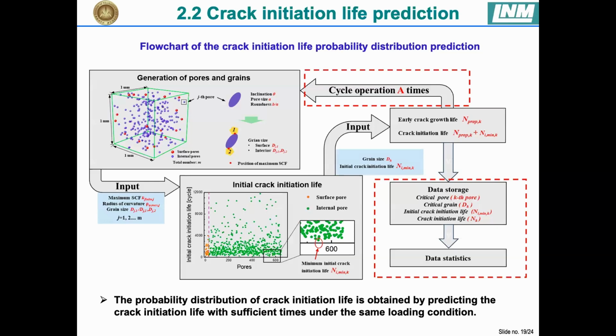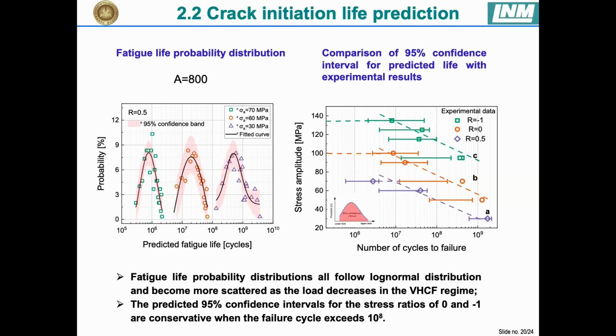In order to obtain the crack initiation life probability distribution, the above steps are cycled sufficient times. And then after each cycle, the data storage and the statistics are conducted. After about 800 cycles, the fatigue life probability distribution can be obtained. It can be observed that the fatigue life probability distributions all follow log-normal distributions at different stress ratios and loading conditions.